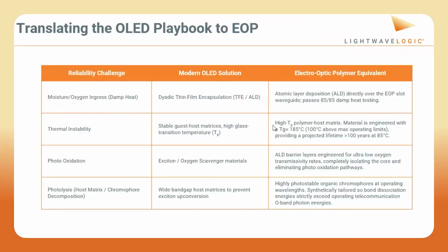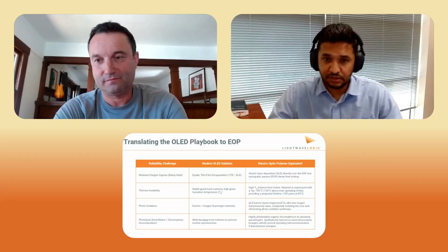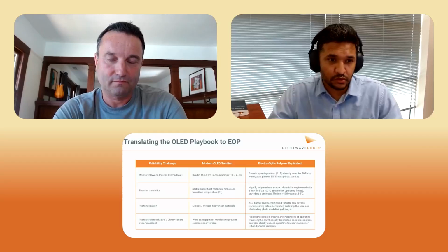So just to kind of wrap it up, we went through our OLED journey, and we learned that the OLED industry in general studied the fail modes and they engineered around them to solve each and every problem. And we kind of drew parallels from that. So like moisture and oxygen ingress, they developed an encapsulation based on ALD. We did the similar thing, and we developed our own ALD deposition on EOP, electro-optic polymers, and that passes 85/85 to show that it works.